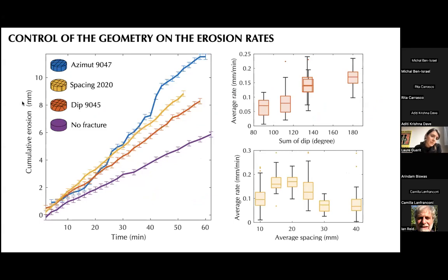So I show here the cumulative erosion for 4 different experiments through time. So in purple here, it's an experiment without any fractures. The others have different geometries. And you can see that as soon as we have fractures, the erosion rate is higher. So here we see a clear impact of the fractures on the erosion rate.